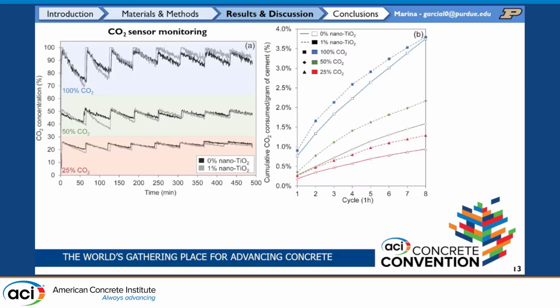And on this graph, you can see the CO2 consumed per gram of cement, so this per cycle. So this relates to the CO2 uptake rate, or how fast we're doing that reaction. And as you can see from these results, both increasing CO2 concentration and nanomodifying the sample did enable more CO2 capture, as well as capture at a faster rate.